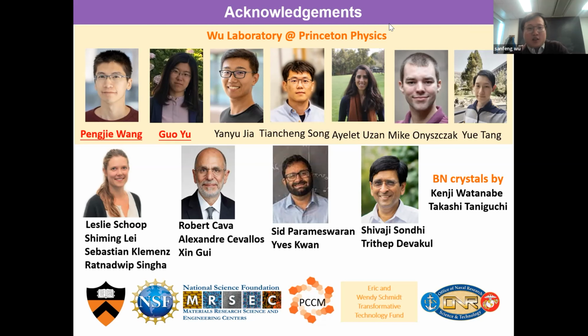Yes, we talk a lot with Ali, standing here. We have done the experiment on the monolayer case, where one of the images I showed is from his lab. Actually, we collaborate. But there are technical barriers that we have to overcome in order to really do it. It's on our list. We're both very interested in this. You can think about it: if you can do a low temperature STM and then vary the gate, tuning it from the electron side to the hole side, I'm sure you will see big changes and see the patterns. The material is air sensitive, so there's something we have to develop before we can get high quality data out of this. But that's ongoing.